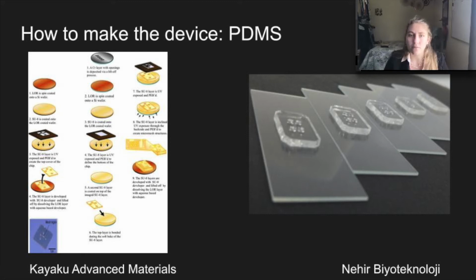and that will take about 10 minutes. And if it's in a plastic petri dish, it's placed in the dryer where the PDMS sets in about 3 to 4 hours. Once the PDMS is set, it can remain in the dryer or at room temperature until one is ready to cut out the devices.